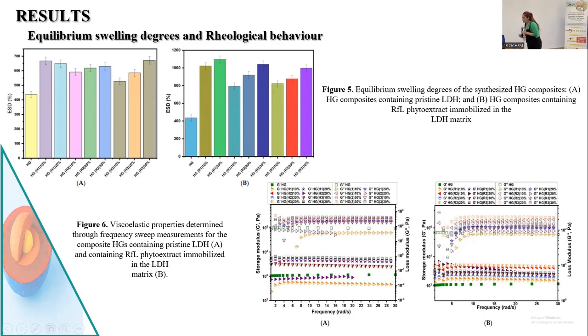due to the LDH intercalated layer inside the polymeric chain of the hydrogel. And also we can observe that the elastic modulus is slightly higher than the loss modulus, a fact that can be attributed also to imperfections of the hydrogel material.